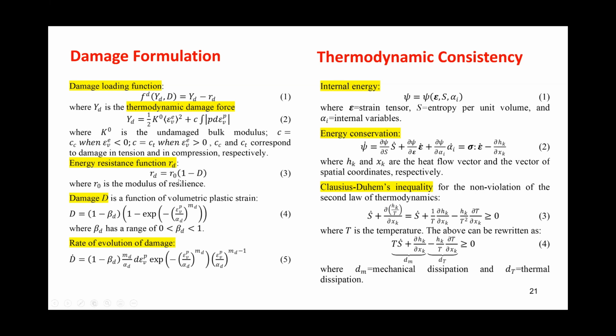Okay, so again, R sub D is equal to R sub O times 1 minus D. And we again use a damage formulation, which is the same, a Weibull distribution of the damage. Okay, and we come up with this damage rule. There is a beta here to control the amount of damage that we have. So if this is equal to 1, it means you completely go to 0 in your residual stress. But if you have a number less than 1, then you can control the amount of residual damage that you can get, and hence the residual shear stress.